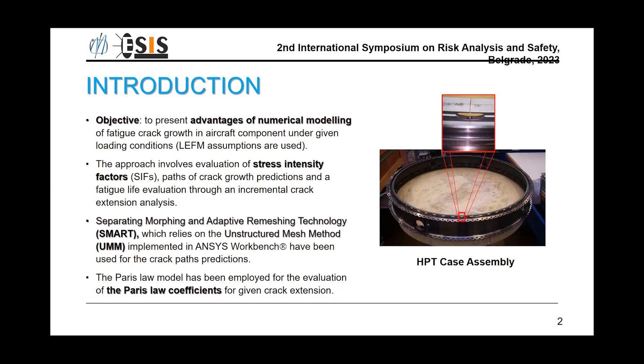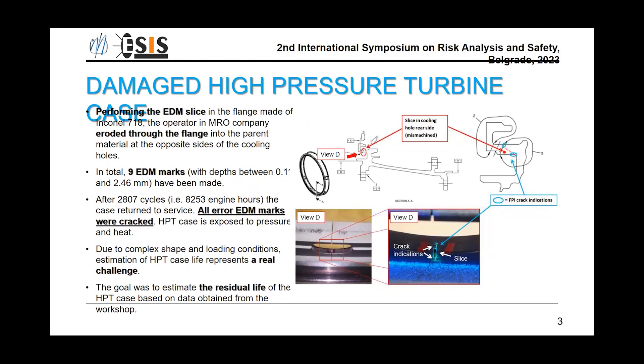This paper deals with damage growth in high pressure turbine cooling holes of the case assembly made of Inconel 718. Several marks were made by mistake in the workshop due to the non-skilled use of electrical discharge machining. In total, nine EDM marks with different depths between 0.1 and 2.46 millimeters had been made. Unfortunately, all EDM marks were detected after 2807 cycles.